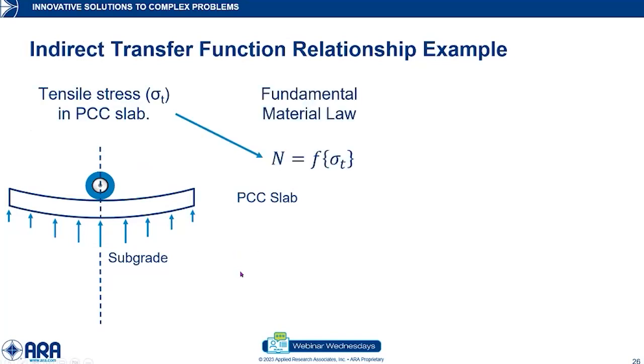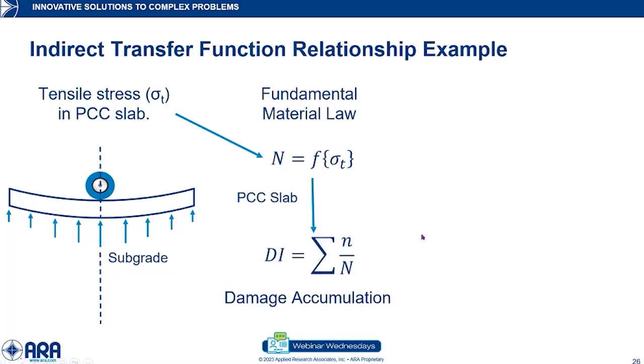And the fundamental material law is going to be a function of the number of cycles you can load it at this particular type of loading, which is a derivative of the tensile stress that you're applying to the concrete slab. I'm showing simplified versions of these formulas. There are other material inputs that are necessary, such as the modulus of rupture for the concrete as well. But the idea here is that the mechanistic response is that tensile stress.